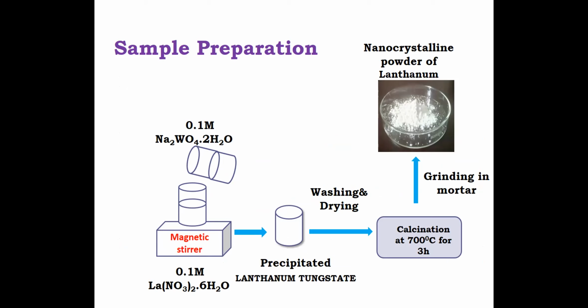Initially, 0.1 molar solutions of lanthanum nitrate and sodium tungstate were dissolved in 100 ml of distilled water separately. The sodium tungstate solution was added to the lanthanum nitrate solution under constant stirring for 15 minutes at room temperature and allowed to precipitate. The unreacted agents were removed from the precipitate by washing with distilled water several times. The obtained precipitate was washed and dried at 70 degrees Celsius for 25 hours using a hot air oven. The obtained product was calcined at 700 degrees Celsius for 3 hours in a muffle furnace to get it in crystalline form, then ground using an agate mortar to obtain the powdered form. It is termed as TB0. For the preparation of the doped sample TB5, lanthanum nitrate and terbium nitrate were taken together as 0.1 molar solution, and the same synthesis procedure is followed.